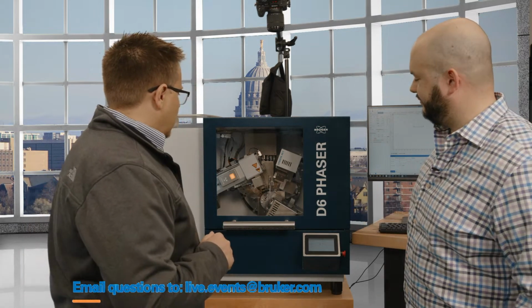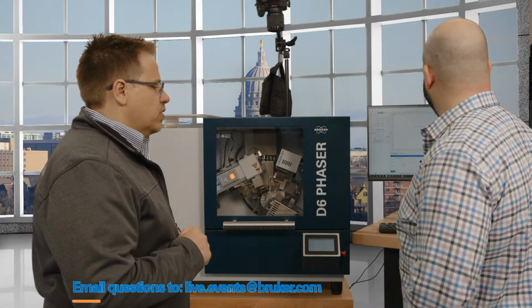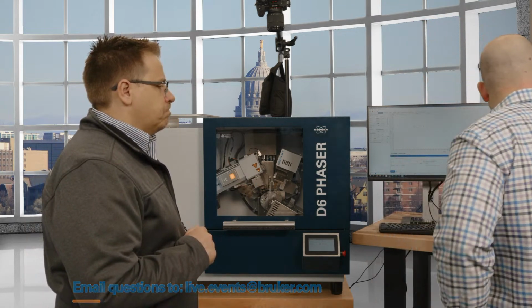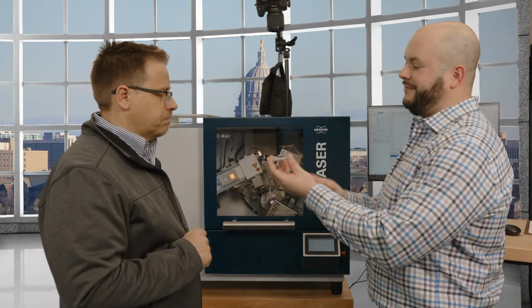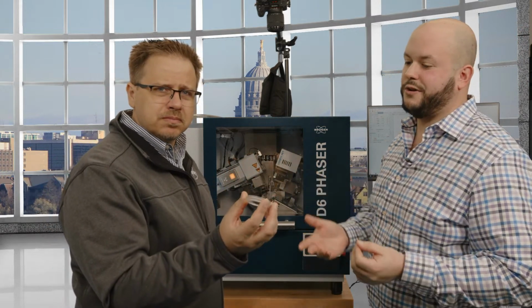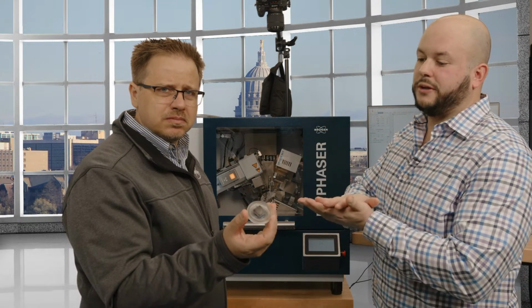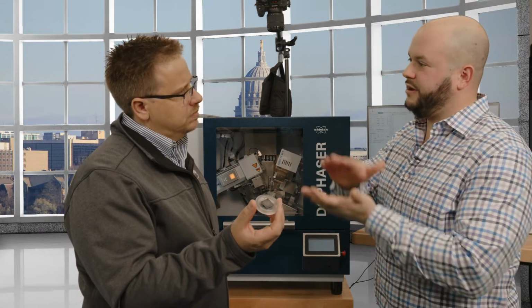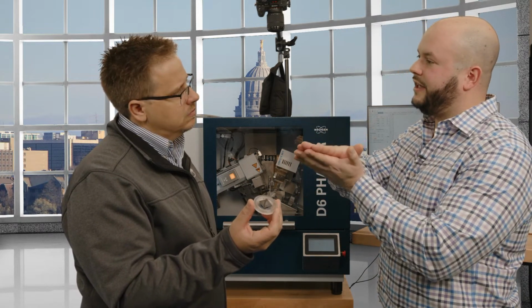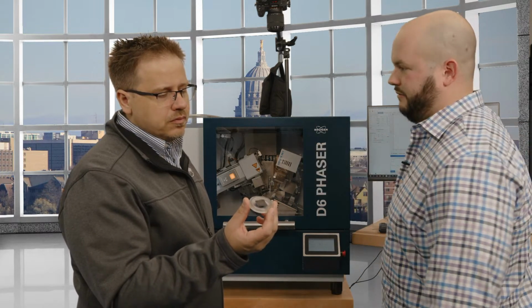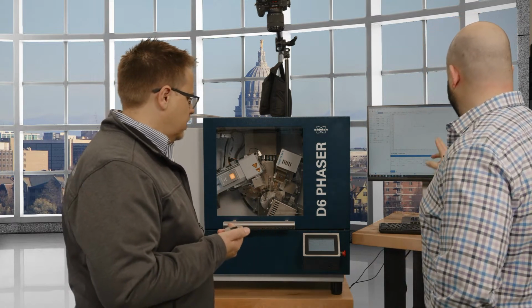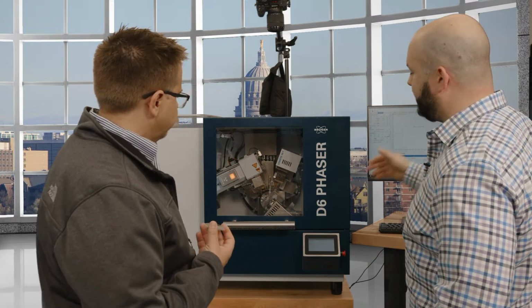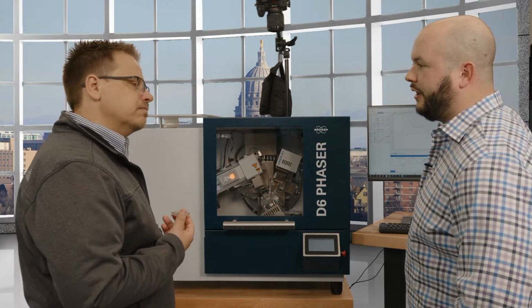So how do we set up residual stress? What's the sample? For residual stress, we have a molybdenum film, and this is actually pretty nice too. If you want to mount bulk samples, we have these well holders, and you can just use a little piece of clay and press it in, so the surface is nice and flat. So there's a piece of glass with some moly on it. And we're going to do some stress. You can see our texture measurement is done, so it's going to go back to park for us.